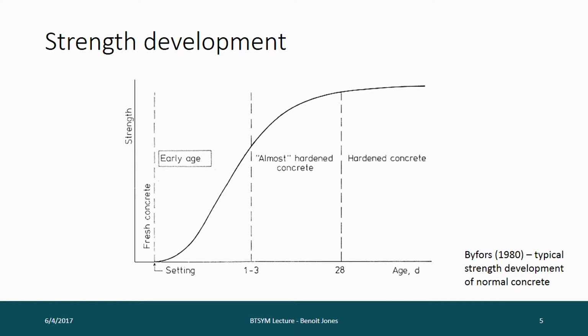So this is a typical strength development curve for concrete. You start off with fresh concrete, it's got no strength at all. And at some point, it sets and begins to gain strength, initially slowly. But actually, reactions between cement and water are occurring before that point. It's just not enough of them have occurred for there to be a rigid skeleton within the matrix of the cement paste. So at some point, enough chemical reactions have occurred for it to start gaining strength.